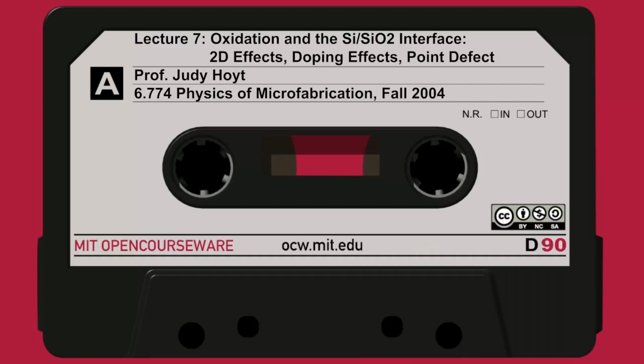And the engineers, the electrical folks, are very interested in the exact shape of this corner. Because it turns out, depending on the exact shape of that corner, and how thick the thermal oxide is, you'll get electric field spikes or buildups right there, or you'll get a region where the oxide is weak and tends to break down. And when the gate goes over that, the device can have breakdown effects, or you can actually cause unusual transistor effects just based on the shape of this corner and this oxidation.